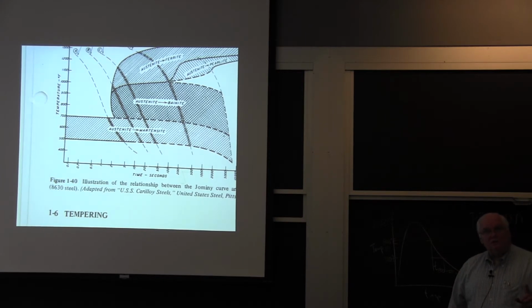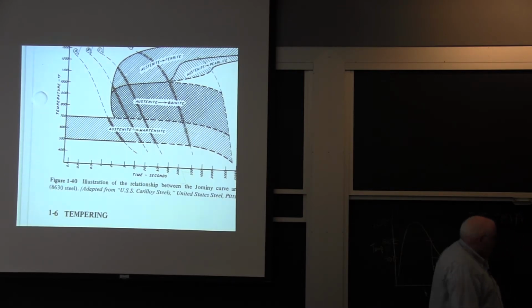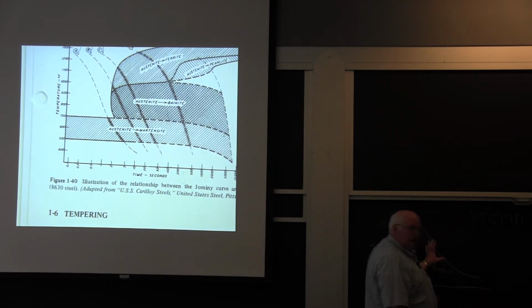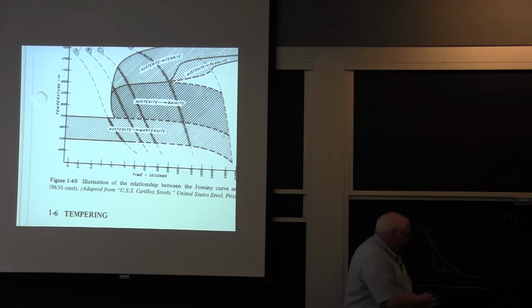You'd have to get any depth of hardenability. But this one's got some depth of hardenability, so you're going to get a higher hardness heat affected zone. And so it's the 800 to 500 that welding metallurgists like to talk about. And that gives you some idea of how long your welding heat is. And with the whole thing quenched, you get through there a lot quicker, because you basically go up about the same in a wet weld, but you come down a lot faster.